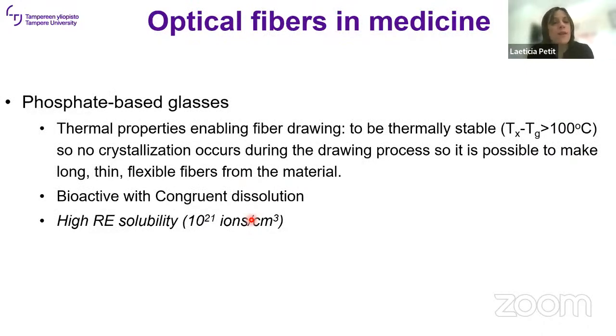One glass system that is quite suitable for this type of application is the phosphate glasses, because you can tailor their composition, so you can tailor their thermal properties, so you can draw them into fibers. For us, we decided that to be a good candidate for fiber drawing, they should be, of course, thermally stable, and we use the difference between the onset of crystallization and the glass transition temperature, and we said that it should be at least 90 to 100 degrees C. So for the glass to be considered a good glass former, no crystallization should occur during the fiber drawing process.